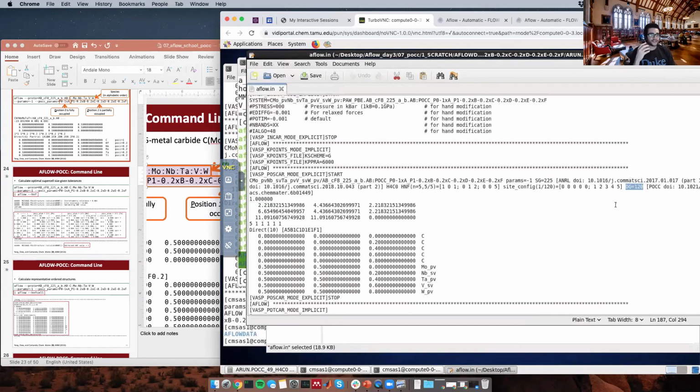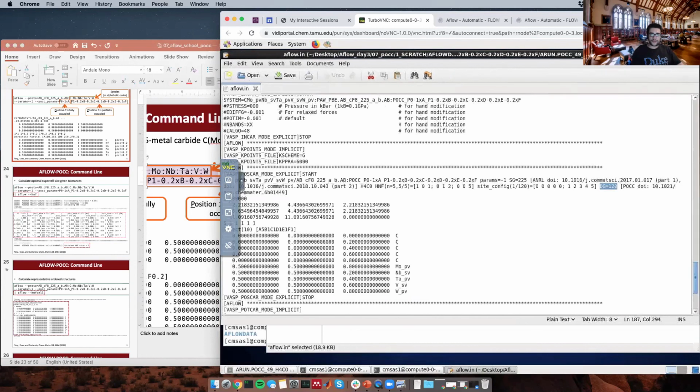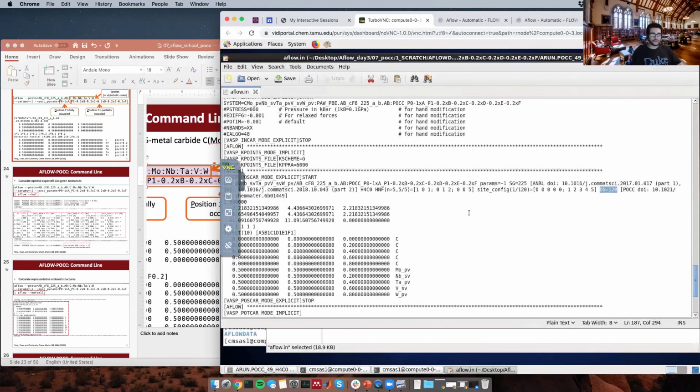So this one's going to have a big weight associated with it because of the degeneracy value. But remember that the weighting also incorporates the energy as an exponential. I know that this structure in particular is not the ground state. So there's a balance: you have degeneracies, but you also have to have the lowest energy to have a good solid weighting for your structure. So a big part of the weighting is the actual energy that VASP gives us for this structure.